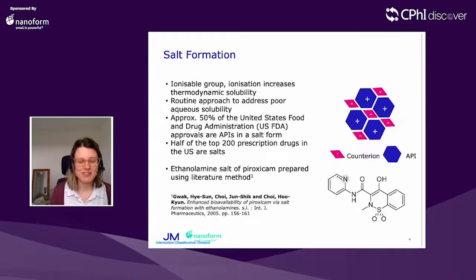So just to give you a background into the different crystal and particle engineering techniques that we used. The first one we looked at was salt formation. Here the idea is that we're ionizing our API, and therefore we would expect it to have a higher thermodynamic solubility. This is a very routine approach for enhancing the aqueous solubility of an API. In fact, around half of all drugs approved by the FDA are in a salt form. For this study, we generated an ethanolamine salt of piroxicam using a literature procedure.